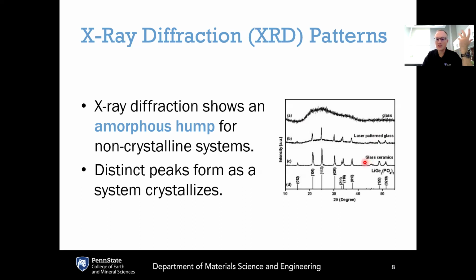There will be a combination of crystal phases and glassy phase. And as a result, the X-ray diffraction pattern will exhibit features from both. It will show peaks, and those peaks correspond to the crystals that have been grown, but it will also have some degree of this amorphous hump, which represents the glassy matrix phase.